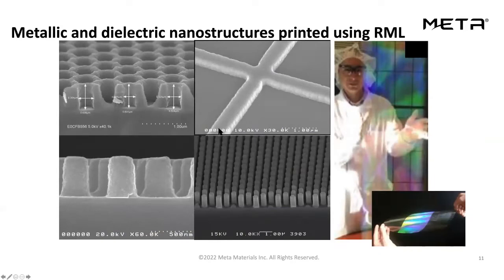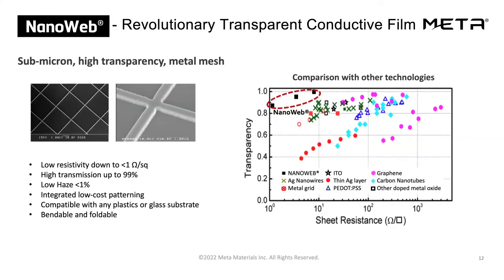So in terms of the structures, we can create, as I said, dielectric as well as metallic nanostructures. And one of the key elements for next generation, high efficiency solar cells is creating ultra high transparency conductive films. We created NanoWeb in this regard, and the chart on the right-hand side shows the transparency versus sheet resistance. Compared to other existing technologies, such as thin film conducting oxides like ITO, as well as other nanowire technologies, we stand alone in terms of the transparency that we can achieve compared to the sheet resistance.